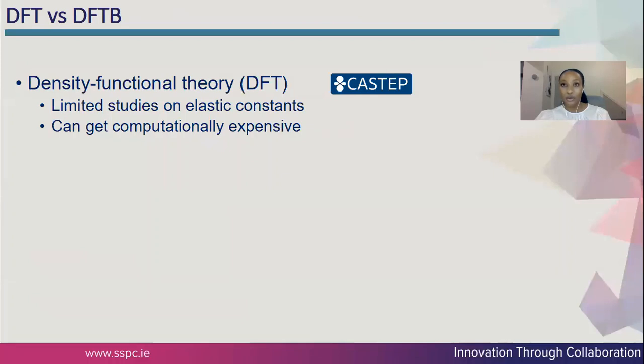But in choosing the appropriate computational method, there needs to be a balance between accuracy and cost. Density functional theory, or DFT, is a widely used state-of-the-art ab initio method adopted even in industry. Ab initio in this case means that the method requires no empirical information about the chemical system. There are also limited studies of elastic constants, from which elastic properties are determined, of molecular crystals using DFT. Although DFT balances accuracy and cost really well, it can quickly become expensive when the size of the system increases. In that case, considering cheaper DFT surrogates that do not compromise on accuracy is a reasonable endeavor.